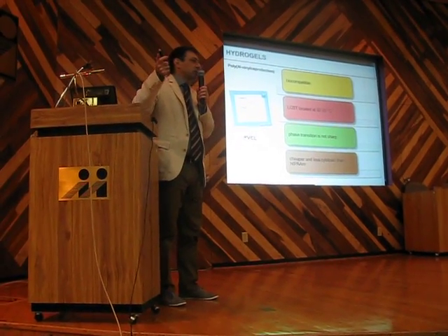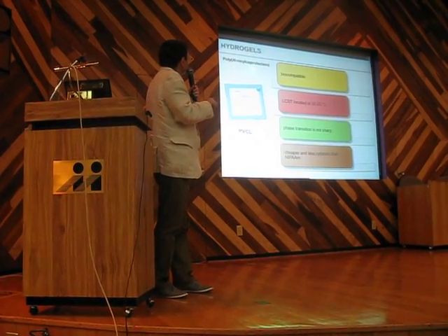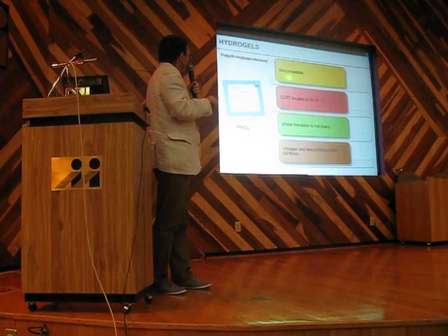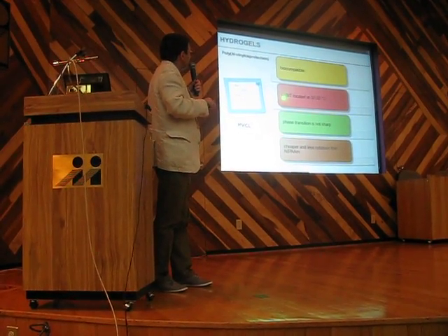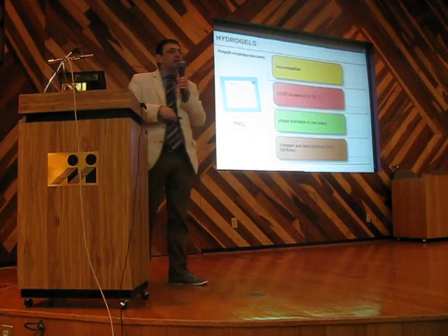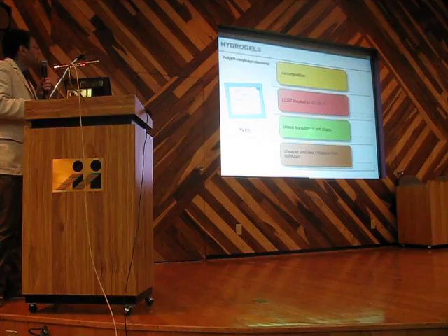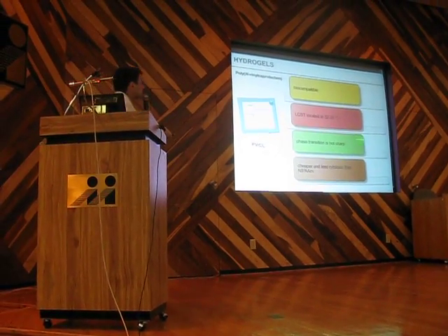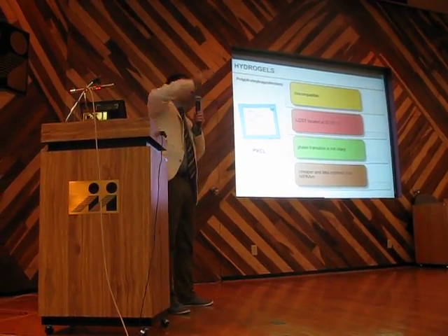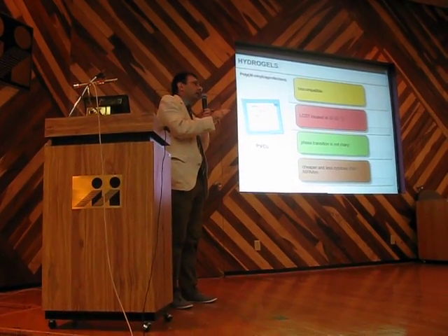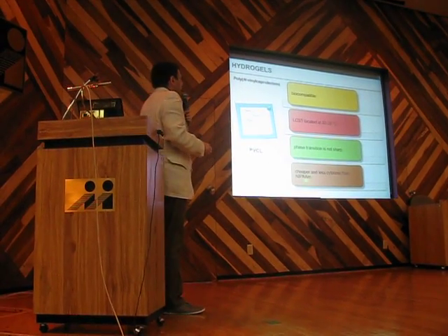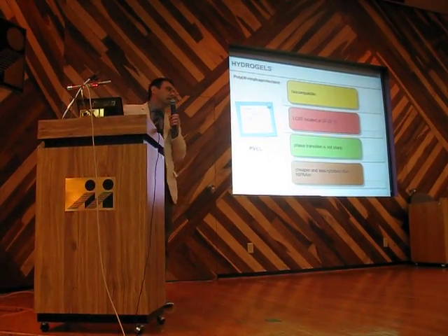We try to copolymerize it by using frontal polymerization with another monomer, vinyl caprolactam, which is biocompatible, which is characterized by more or less the same lower critical solution temperature at 32-33 degrees, but which does not have a sharp transition between the swollen and the deswollen states. However, it's cheaper and less cytotoxic than NIPAM.